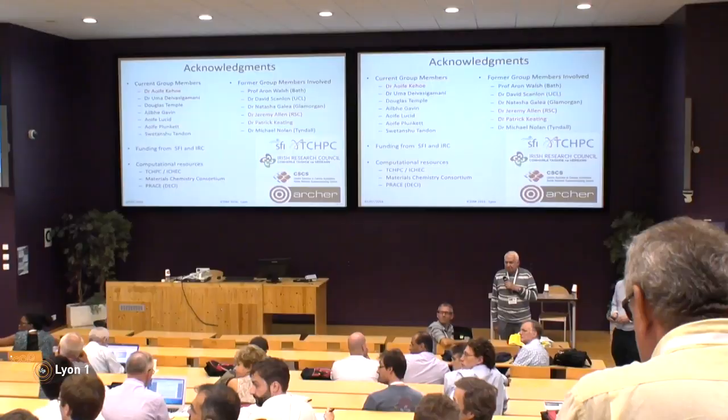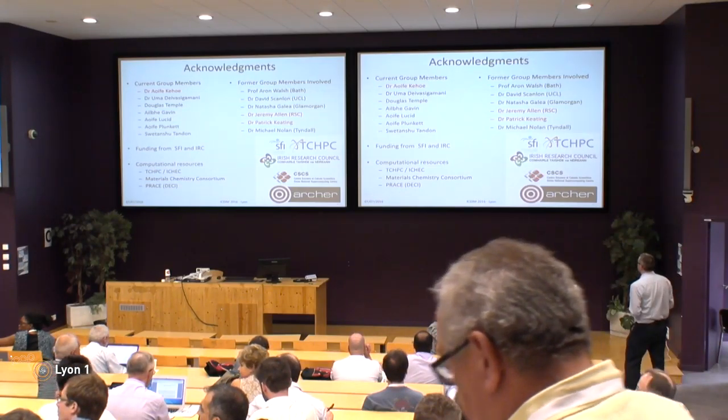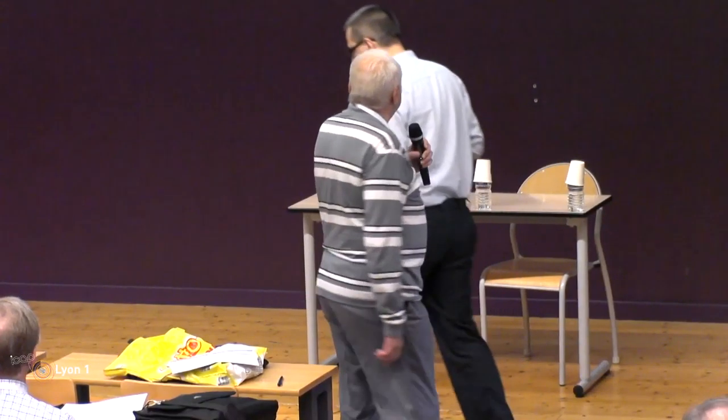Question: Do you apply any defect-defect corrections, given the small energy differences? Answer: These are relative defect energies. We haven't done any cell-to-cell periodic corrections in those cases — the defects are neutral, so there are no charge corrections. We could use a bigger cell to reduce the interaction of the distortions with each other; the likelihood is the corrections would be very small, but this was more of a test of principle. Additional comment: The supercell used was only 96 atoms (2×2×2), so defect-defect interaction convergence would need to be checked. The calculations were intended as a demonstration of the occupation matrix principle rather than a definitive calculation of the oxygen vacancy energy.